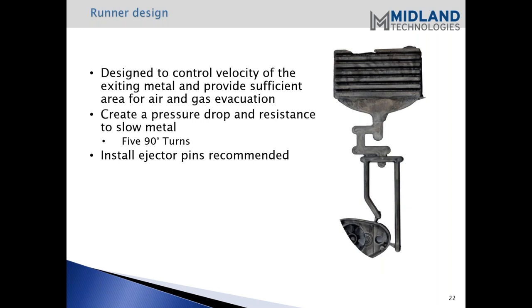Because calculations are based on fill time and volume, and also driven by alloy, you could end up with a very large - say, eight-inch - block attached to a very small part because the cavity fill time is so low. Magnesium has a very rapid solidification process and you've got to fill the cavity quickly. You can be down in the 5 to 15 millisecond fill time. With that fill time and the volume of the casting, you may have to go to a larger block. Larger castings may not require as large a block - we're driven by volume and fill time.